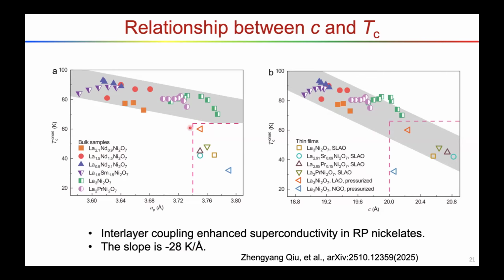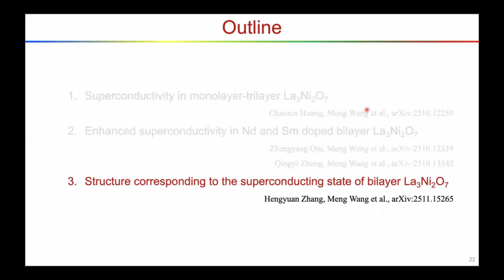But if we look at the in-plane lattice constant, the bulk samples do not have the same slope as thin film samples. So we think the interlayer coupling is more important for the transition temperatures of the RP nickelates. Okay, I will quickly introduce the last part, the structure corresponding to superconductivity of the bilayer nickelate.